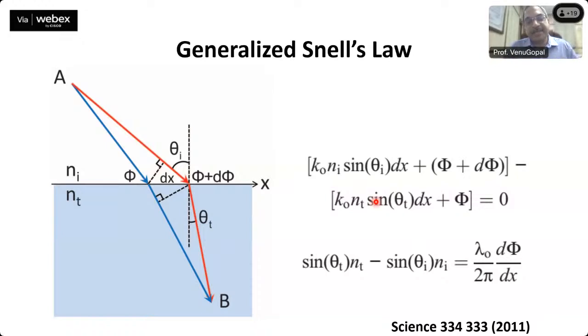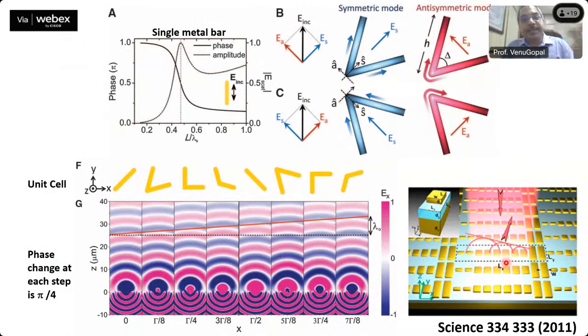From Snell's law, a generalized Snell's law comes out, if you have a surface which is patterned or having antennas or complex structure. You can have a spot coming in, and because of the ellipticity you'll always see a difference in the phase from the two edges, and that can be manipulated by structuring your surface. So if we take that additional phase difference across the beam into consideration, Snell's law is generalized to have this sine theta t times nt, this is in the refraction or the transmission direction, minus the incident one, sine theta i times ni. These are the refractive indices of the incident and the transmitted media, and lambda 0 is the vacuum wavelength, so lambda 0 by 2 pi times the phase gradient. So this is the additional factor which comes in if you want to consider a metasurface or patterned surface. Right. So people have shown these kinds of structures.